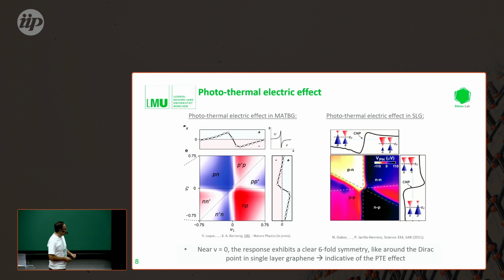So in order to convince ourselves that this is really the photothermoelectric effect that we read out, we can focus on the charge neutrality point here, where we observe this very characteristic six-fold structure, where of course we get a sign change between PN and NP regions, as expected from many photovoltage effects. For example, the photovoltaic effect will give us the same. But the hallmark of the Seebeck effect, of the photothermoelectric effect, is that also in the same polarity regions, so in PP', P'P, and also on the N side, we see a sign change within this quadrant, and this is only achievable through the photothermoelectric effect. Similar studies have previously been done by the Pablo Jarillo-Herrero group to show that the six-fold pattern is the hallmark of the Seebeck effect in single-layer graphene as well.